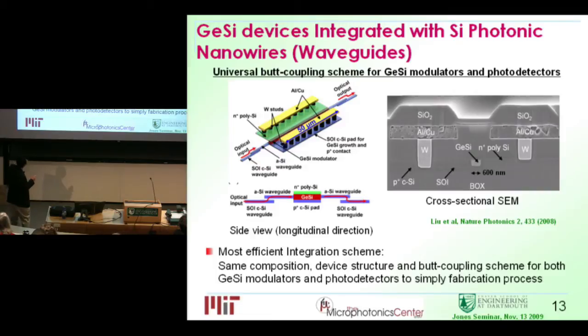In other cases, when you don't want to do the modulation, you just want to convert the photons into electron hole pairs, you can make this path longer. So you absorb all the photons, and then you get photocurrent. So this is a cross-section SEM picture. So you can see the germanium core is here, only 600 nanometers wide. So the benefit is that we can use the same device structure, same material, and one-step processing for both devices.